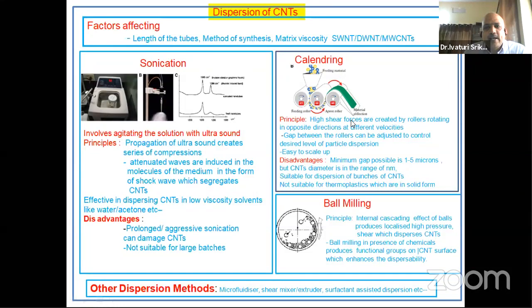The second one is a calendaring technique, where you can see there are three rollers. The center roll is rotating in the opposite direction to the other two rolls. So this creates some shear force between the rollers, and the nanotube or nanometal mixed resin system is poured at the interface of these rollers. Because of the shear force experienced by the filler added resin, the dispersion of the nanotubes takes place.